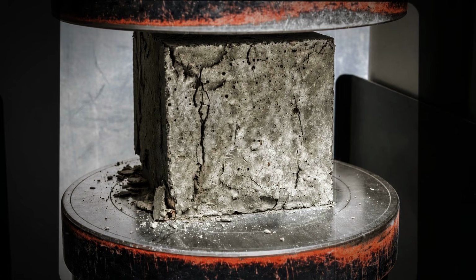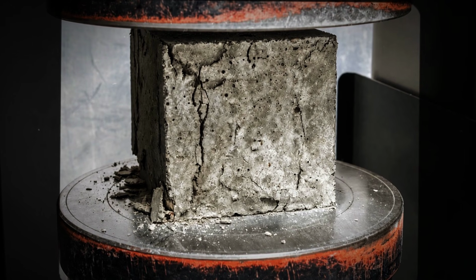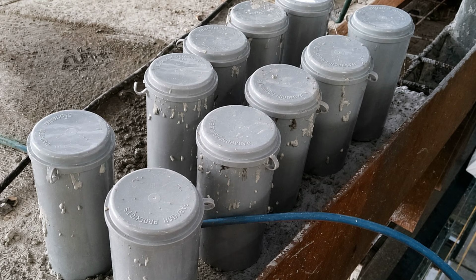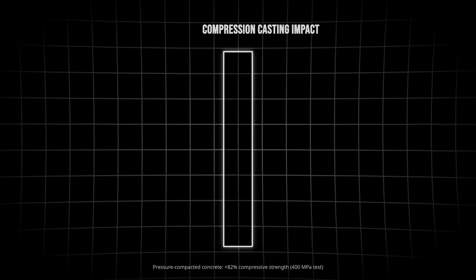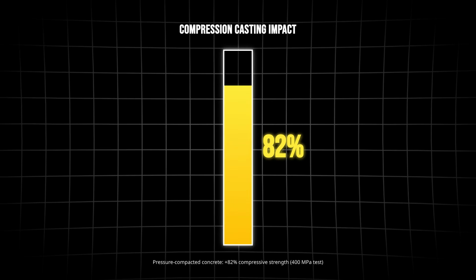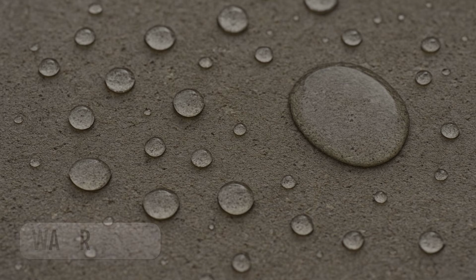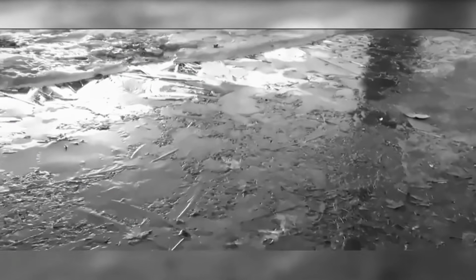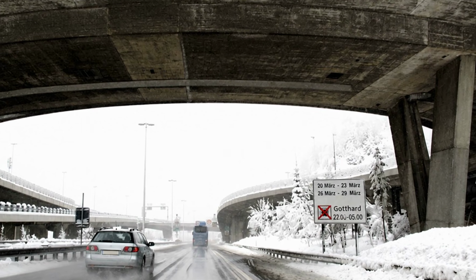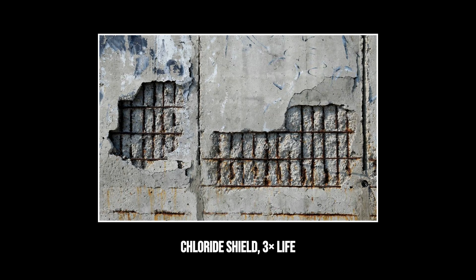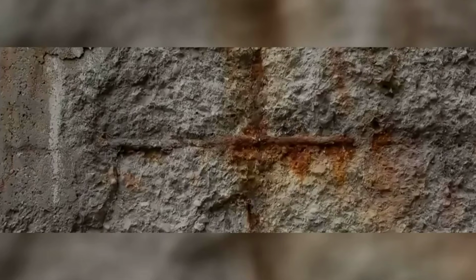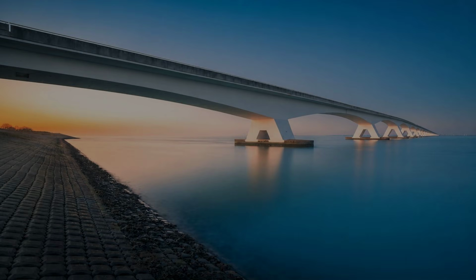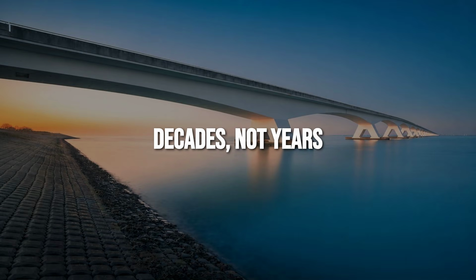The consequences cascade. A 45% reduction in porosity does not produce a 45% increase in compressive strength. The relationship between density and strength in concrete is nonlinear. At the highest pressure ranges tested, compressive strength increased by over 80% relative to identically proportioned standard concrete. Resistance to water intrusion improved substantially. Resistance to freeze-thaw cycling, the mechanism responsible for a significant share of infrastructure deterioration in cold climates, improved. Resistance to chloride penetration, the process by which dissolved salts migrate through concrete and initiate corrosion of steel reinforcement from the inside outward, improved to a degree that projected service life extensions measured in decades rather than years. Same cement, same stone, same water, different handling.